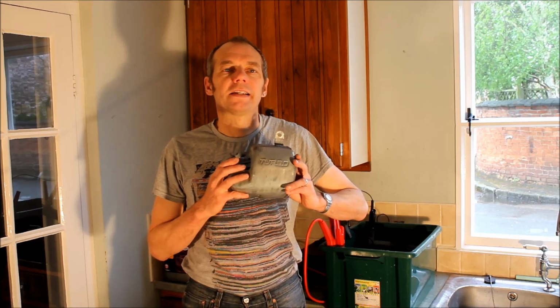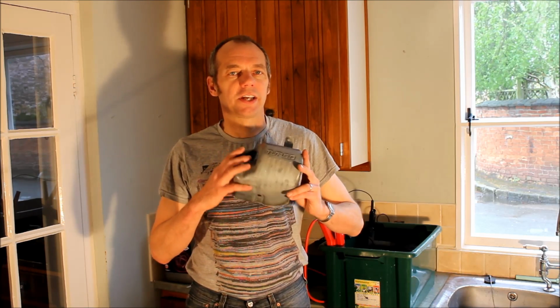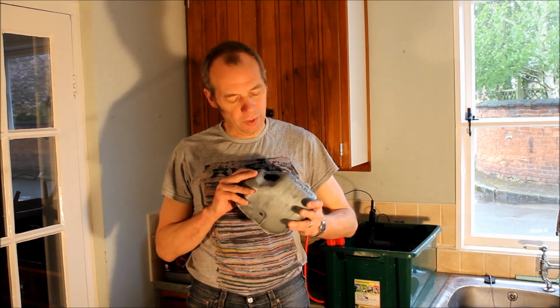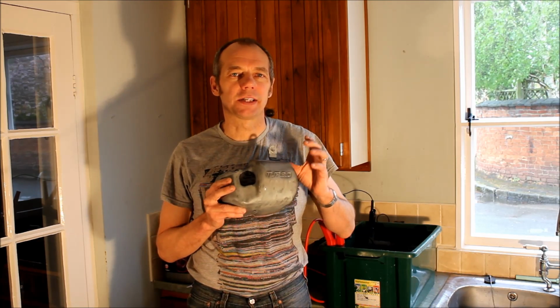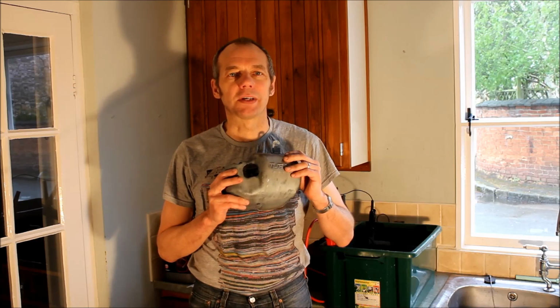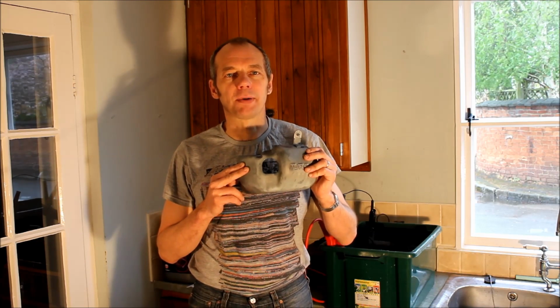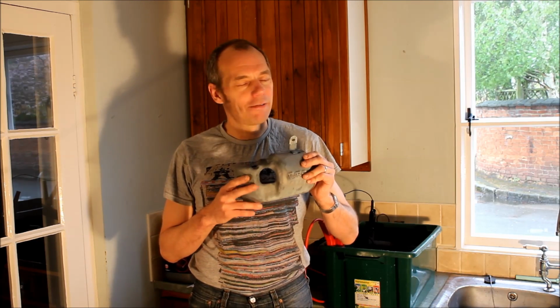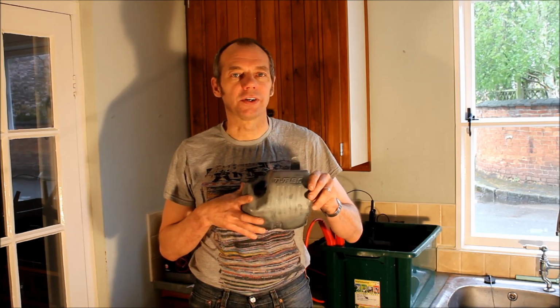The problems with plating this are twofold. Firstly is just the size and the shape of it. It's about 1,000 square centimetres in area, and that means that normally you'd expect to use a plating current of about 15 amps to get a 25 micron thickness of plate in about 70 minutes. However, it just won't stand anything like that sort of current just because of the shape of it.